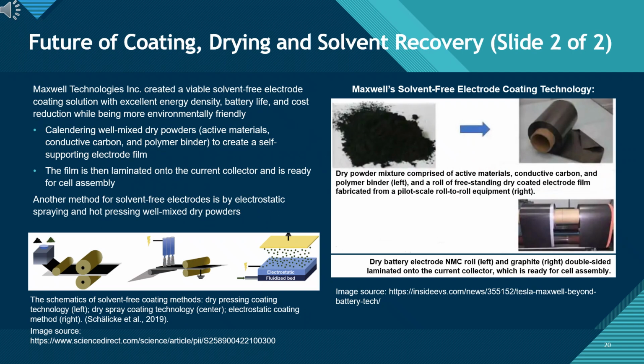Future of coating, drying and solvent recovery, Slide 2 of 2. This slide introduces emerging solvent-free electrode manufacturing technologies designed to cut costs, reduce energy use, and eliminate NMP from the coating process. Maxwell Technologies has demonstrated a dry electrode process in which well-mixed powders, active material, conductive carbon, and binder, are calendared into a self-supporting film.